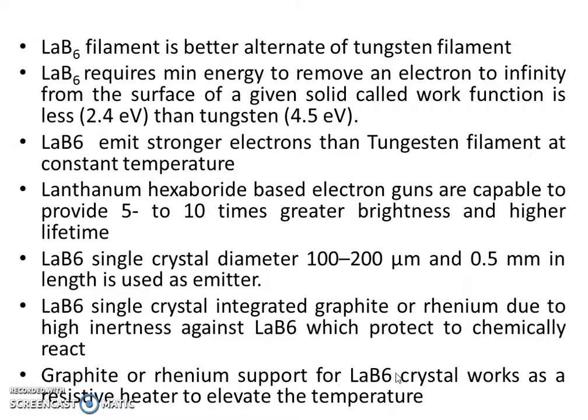LaB6 filament is a better alternative to tungsten filament. LaB6 requires minimum energy to remove an electron to infinity from the surface of the solid, called the work function, and the work function is less than 2.4 electron volt, compared with 4.5 electron volt in the case of tungsten. LaB6 emits stronger electrons than tungsten filament at constant temperature. Lanthanum hexaboride based electron guns are capable of providing 5 to 10 times greater brightness and a higher lifetime.